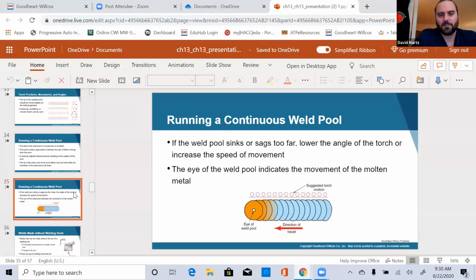Running a continuous weld pool or puddle. If the weld puddle sinks or sags too far, lower the angle of the torch or increase the speed of the movement. The eye of the weld puddle indicates the movement of the molten metal. So if we're doing the circles, we want to keep them in. Everything's going to work together in a tight working space. If our puddle starts to droop through, we're too hot, our flame needs adjusting, or we're too close to our base metal. If our puddle starts to get too wide and out of control, we're going too slow and need to speed up. If our puddle gets too narrow and thin, we're moving too fast and not taking enough time. So our bead can tell us a lot about our weld, whether we're moving too fast or too slow, too hot or too cold.